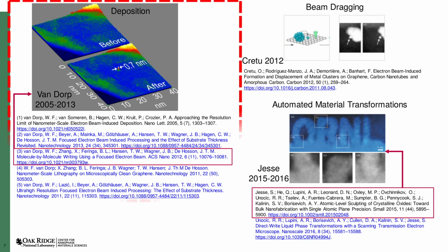From 2005 to 2013, Van Dorp et al. published a series of papers describing how they were able to perform electron beam-induced deposition in a STEM. This is typically performed in an SEM with lower resolution, but with the sharp focused beam in the STEM and using single-layer graphene as the substrate, they were ultimately able to deposit material molecule by molecule. This was in no small part enabled by the great lengths they went to ensure stringent sample cleanliness.